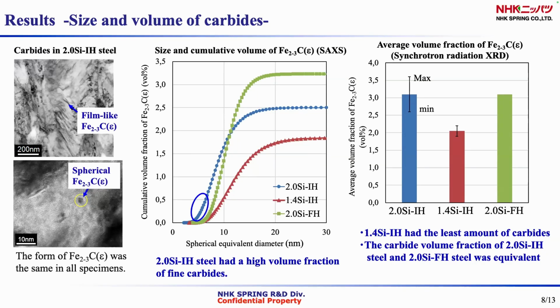This figure shows the relationship between size and cumulative volume of epsilon carbide. As you can see, the high-silicon steel still had a high volume fraction of fine carbides. And this figure shows the average volume fraction of epsilon carbide. 1.4 silicon IH still had the least amount of carbides. On the other hand, the carbide volume fractions of 2.0Si-IH and 2.0Si-FH were found to be equivalent.